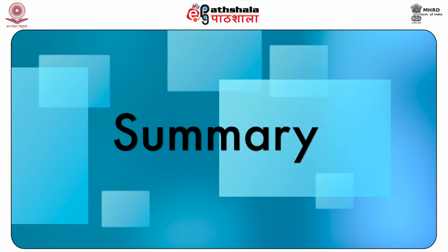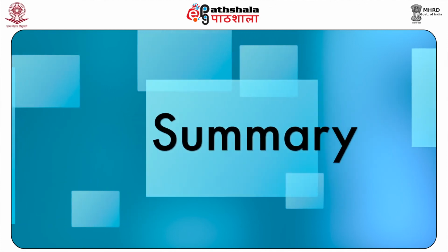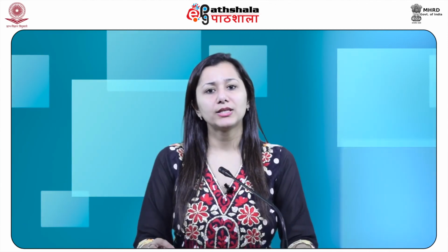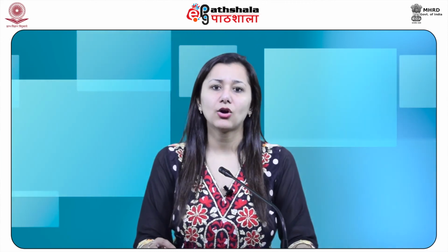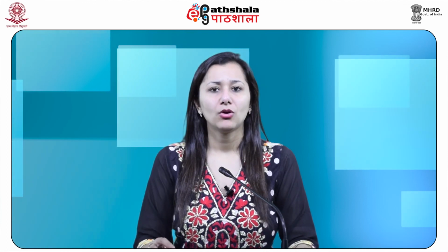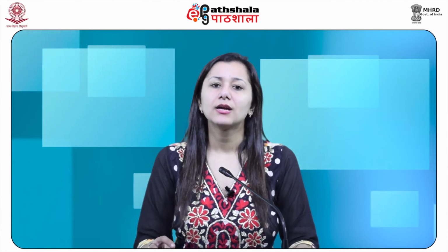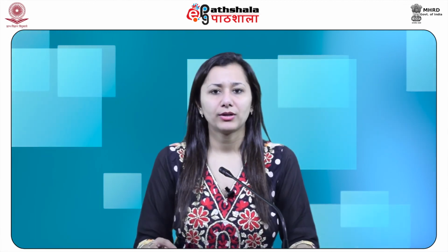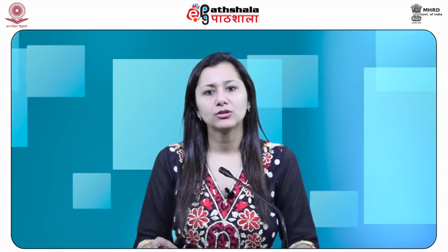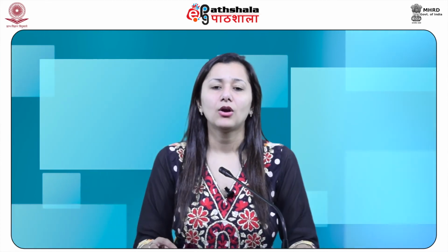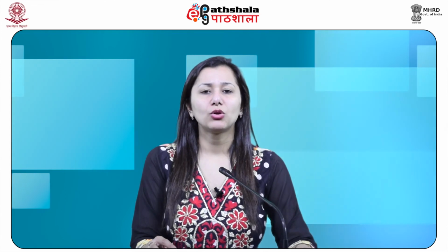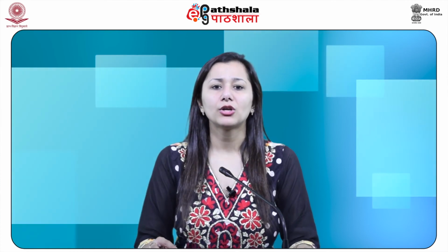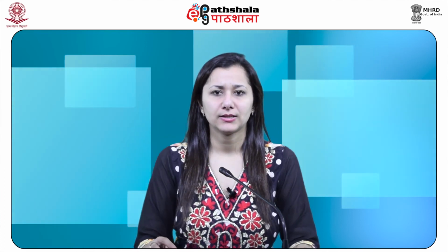Now, we shall summarize what we have learnt in this module. The number average molecular weight assumes prime importance in the context of studies of solution properties that go by the name of the colligative properties, that is, vapor pressure lowering, freezing point depression, boiling point elevation, and osmometry. On the other hand, weight average molecular weight assumes importance in context of various bulk properties of the polymers, particularly the rheological and the resistance properties.